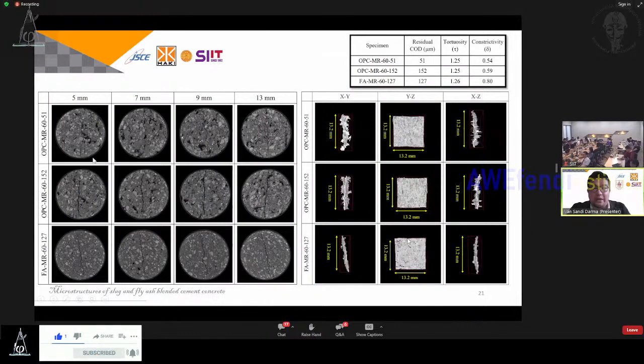As you can see here, this is the crack geometry. We have three samples. First, OPC with lower crack opening width, here 51 micrometer. The second one, OPC with 152 micrometer. And the last, a fly ash specimen with 127. This is the image from 5 millimeter, 7 millimeter, 9 millimeter, and 13 millimeter from bottom to the top.